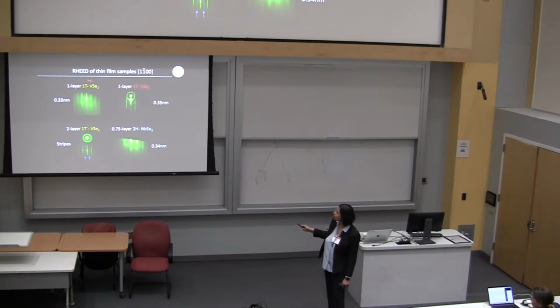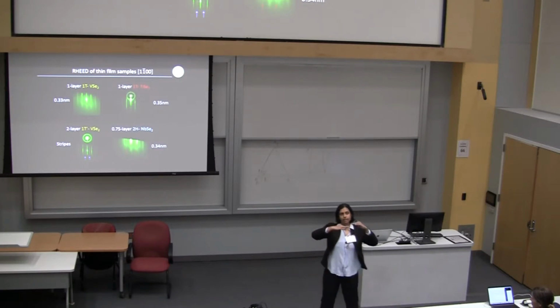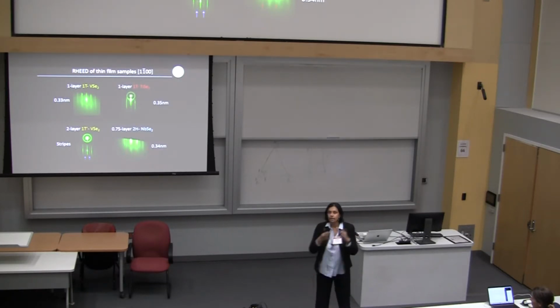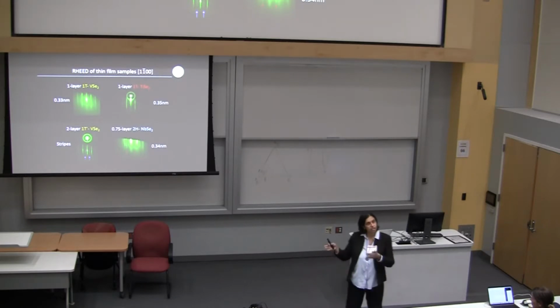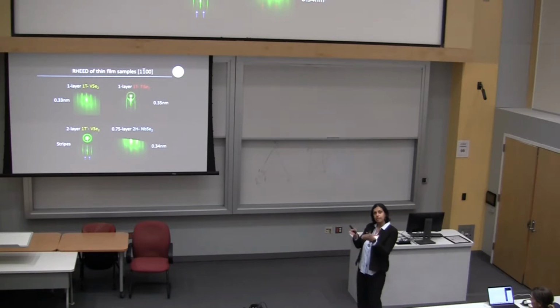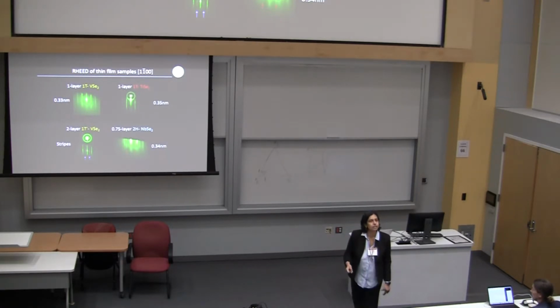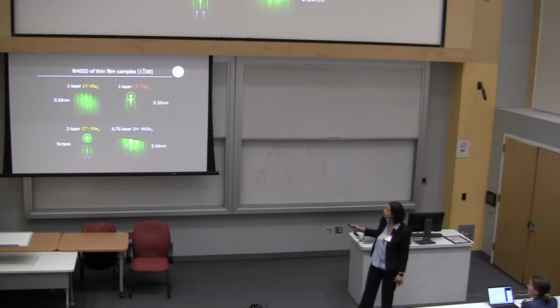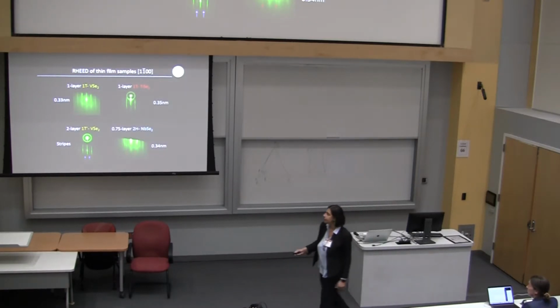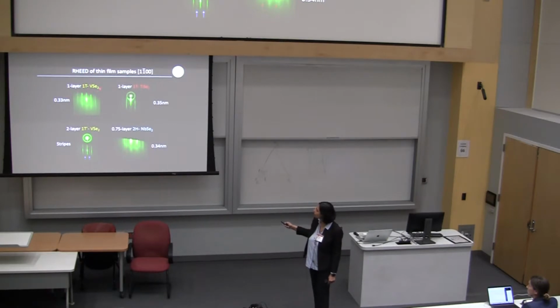One interesting thing is going from 1T to 1T prime. I don't know if you remember, in 1T prime, you have the chalcogens going up and down and up and down. That doubles your real space periodicity in one direction. So in Fourier space, you get these extra streaks at half the periodicity. So at least you can tell the difference between 1T and 1T prime. Okay? So look at this. We've been able to grow both 1T and 1T prime vanadium diselenide, and we did this simply by changing the growth temperature.